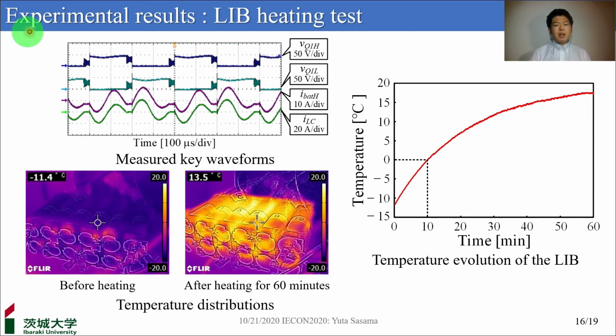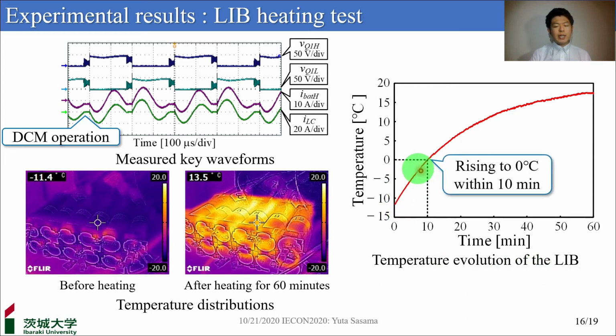Here, you can see the experimental results of the lithium-ion battery heating test. These waveforms agreed well with the theoretical ones and verified the DCM operation of the prototype. The bottom left pictures show the temperature distribution observed by the thermography. These pictures demonstrated that the temperature increased by flowing AC current in the battery. This graph shows the temperature variation of the battery. The temperature of the battery rose to 0 degrees within 10 minutes. These results demonstrated that the proposed converter could heat up the lithium-ion battery by AC heating.